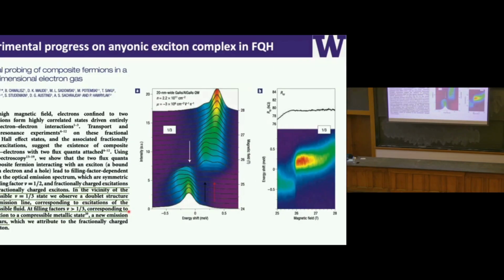And there are a lot of experiments being done in the community. Here I highlight one of the experiments. This is the closest to what I'm going to show you in my talk, right? This is a photoluminescence measurement of gallium arsenide samples. We can focus on this panel first, right? This black curve is the transport measurement. They measure R_xy as a function of magnetic field. You can think of it as tuning the filling factor in the Landau levels. So this magnetic field corresponds to 1/3 filling, all right?